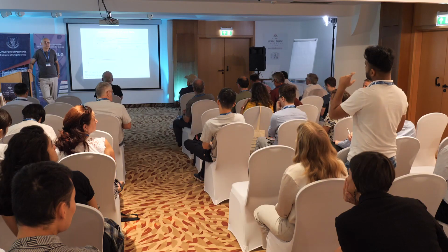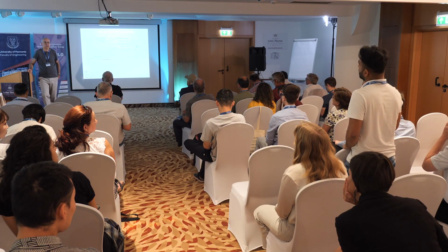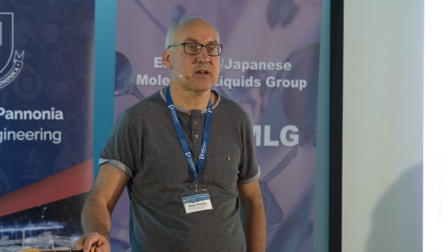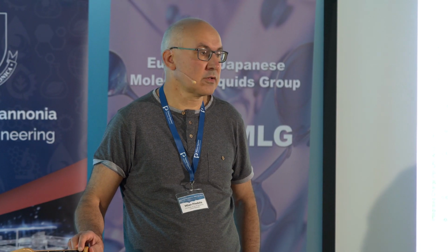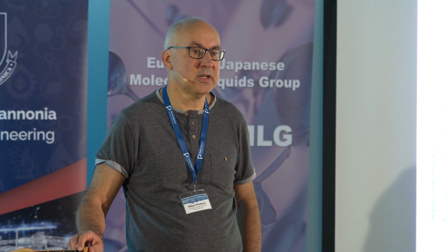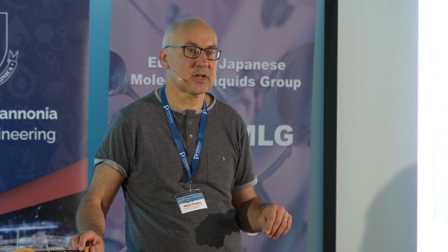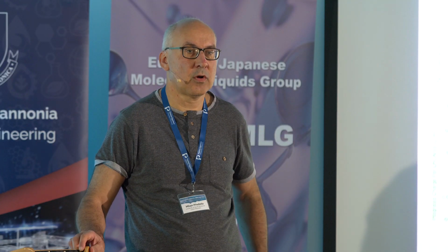Then how much was the thickness of that Stern layer? Typically, it was really up to 15-20 angstroms from the surface, because we typically used concentrations up to, let's say, 0.4 molar. And even what I call 0 molar meant that we needed to have counter ions, which were basically at a concentration of something like 0.06 molar.